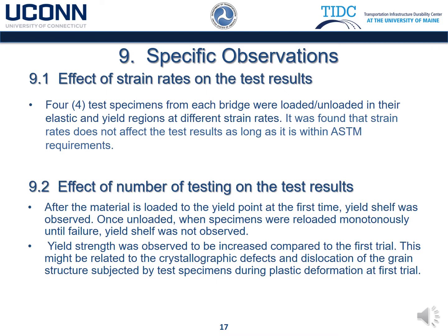Specific observations. Effect of strain rate on test results. The four specimens from each bridge that were loaded and unloaded have shown that the strain rate does not affect the test results, as long as it's within ASTM specifications. Effect of number of testing on the test results. After the material gets loaded to the plastic region and unloaded, the yield shelf was not observed and strain hardening was observed. This behavior is expected for most metallic materials.